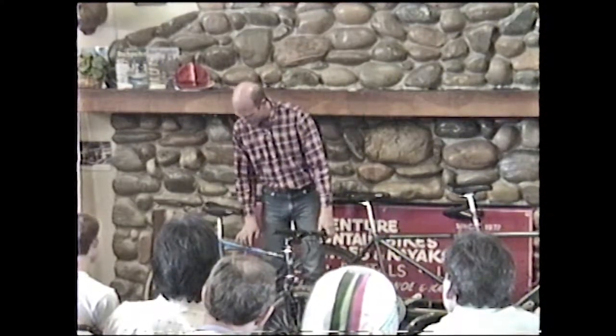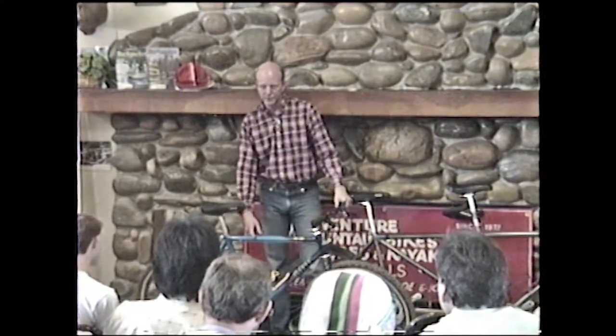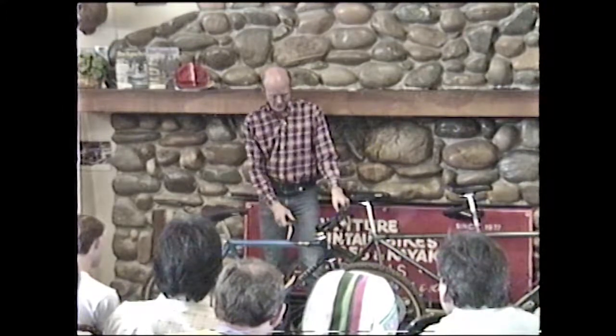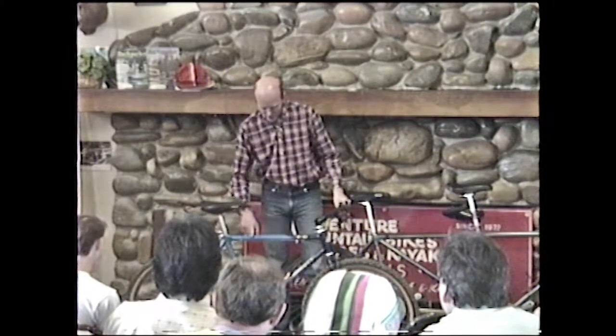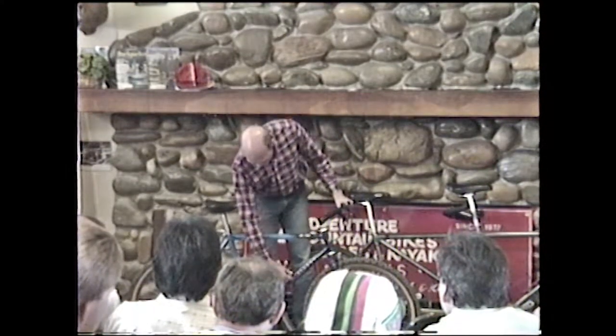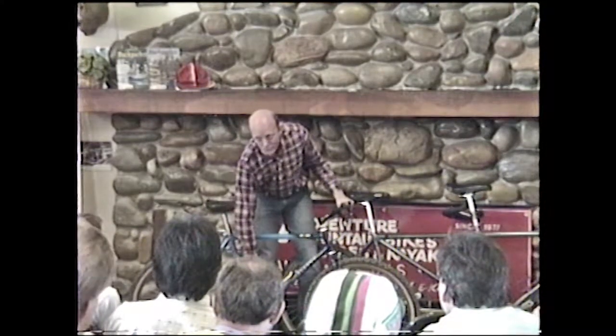This year's bike, we've also changed in that we went to a larger diameter top tube. We went 1 1/4 seat tube, 1 3/8 down tube. This is a set that we designed with True Temper, and it's a new heat-treated version for them, and it's a quad-butted tube set. What I mean by quad-butted is simply that it's a 1 millimeter wall, becomes a 0.8 millimeter wall, becomes a 0.6 millimeter wall, and then back to a 0.9 millimeter wall here.